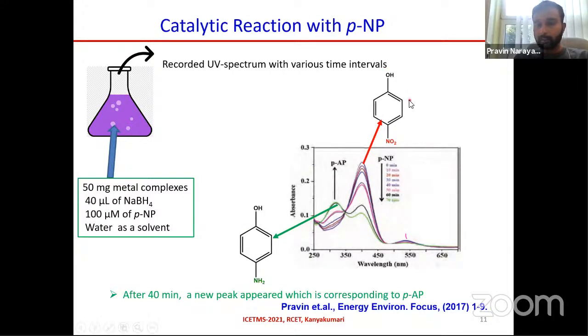So this is the para-nitrophenol, and the peak is observed at 400 nanometer. After a particular time, you can see that the absorption of the para-nitrophenol peak gradually decreases, and a new peak is formed around 310 nanometer, which corresponds to para-aminophenol. And the isosbestic point clearly states that no side reactions or side products are formed. After 70 minutes, the para-nitrophenol is completely converted and para-aminophenol is formed.